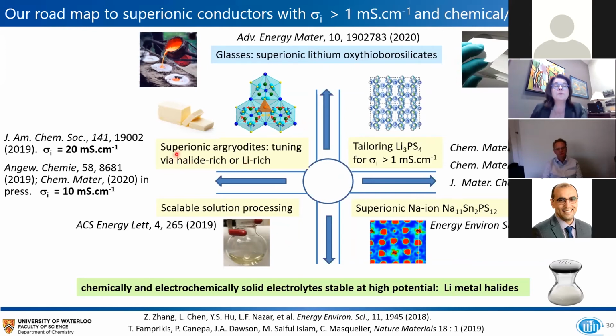We've also tried to tune a well-known structure called the argyrodite, and I'll be talking about that on the next slide. And we've done that by making the material halide rich, and thus changing the sulfide, which is an S2- ion, for a halide monovalent ion. And that really reduces the interaction of the lithium cation with the anion in the framework. And so the picture of butter is meant to indicate that it eases the transport. And indeed, we've managed to obtain conductivity similar to that material LGPS, in other words, upwards of 10 millisiemens by this approach with very high diffusivities.